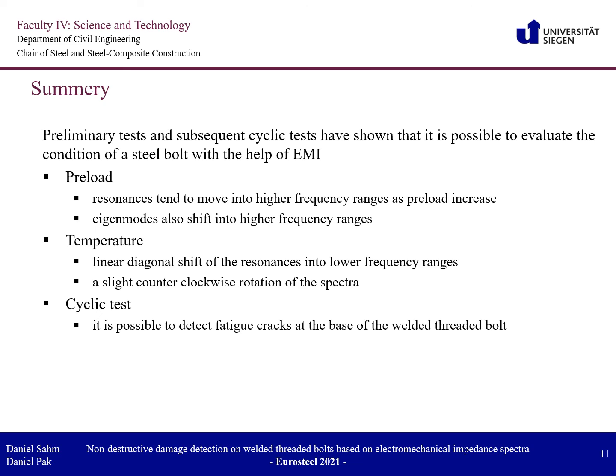Finally, I would like to give a little summary of the results. The preliminary tests and subsequent cyclic tests have shown that it's possible to evaluate the condition of a steel bolt with the help of EMI. The preload tests have shown that the resonance tends to move into higher frequency range as preload increases. We also could see that the eigenmodes also shift into higher frequency range. The results from the temperature tests are the linear diagonal shift of the resonance into lower frequency range and a slight counterclockwise rotation of the spectra. From the cyclic test we can see that it's quite possible to detect fatigue cracks at the base of the welded threaded bolts.